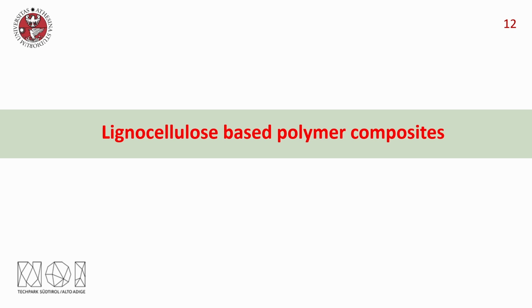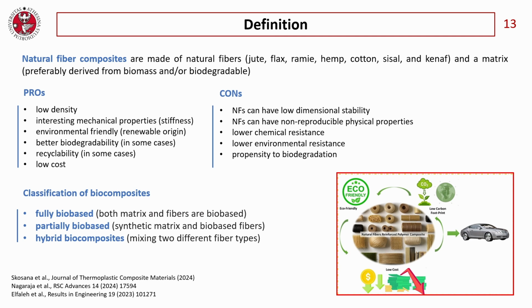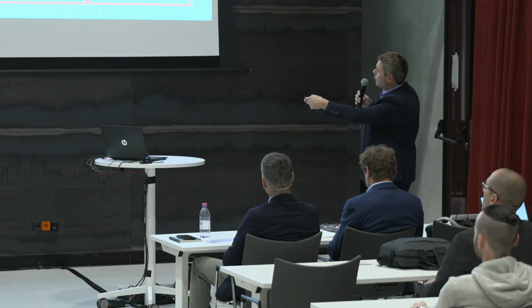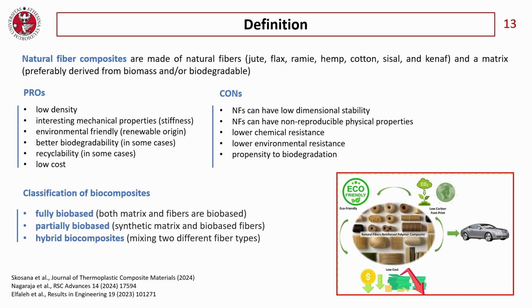So now we can pass to the composites that we can make with this lignocellulosic reinforcement. This kind of material, natural fiber composite, can have some advantages like low density, interesting mechanical properties in terms of stiffness, renewable origin, potential biodegradability, recyclability in some cases, and a lower cost. But they also have some challenges, some drawbacks. In particular, low dimensional stability. Natural fibers can have non-reproducible physical properties, lower chemical resistance, lower environmental resistance, and a propensity to biodegradation that in some cases could be a negative issue.